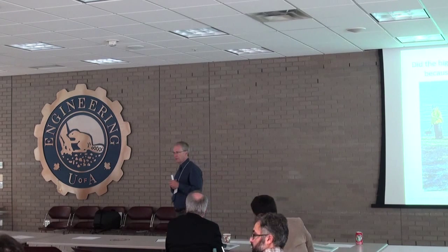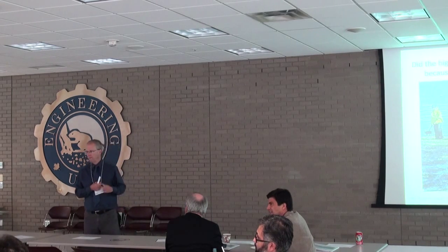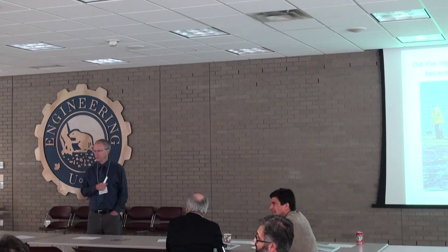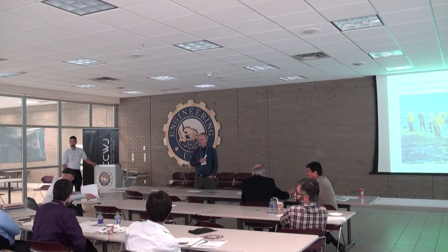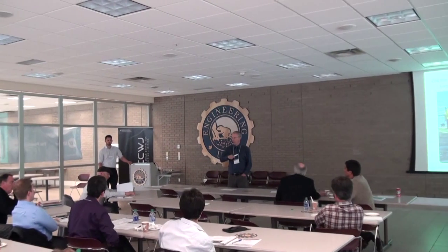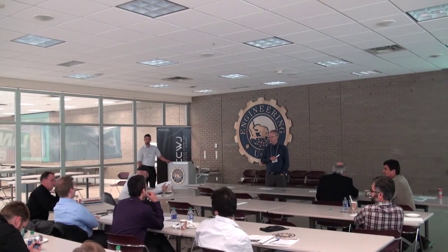Yeah, in my past experience, we had some high carbon material to weld on. We had the manufacturer make us up material with a similar carbon equivalent, and that's what we qualified and did our procedure on. You have to have something made that's got that high of a carbon to match the stuff that's in the ground. You want to be as high or perhaps higher on your carbon. We got a sample of material, did our procedure, did the test, and away you went.